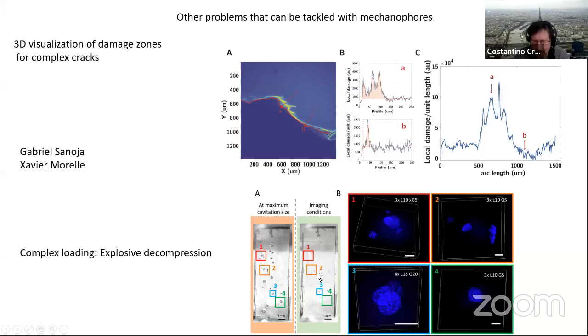And the second example is, I think for me, another fascinating case: cavitation, the explosive decompression. You saturate the rubber with gas, and then once it's saturated, you decompress rapidly. This is something that the oil and gas industry does. And then all these cavities close down, so you have no idea that these cavities ever existed. But now if you have a mechanophore, you can look at the sample with cavities closed and observe the shape. One of the things that we found is that these cracks actually have disk-like shapes. They do grow as cavities, but the damage zone is very much a disk, like a penny-shaped crack. And we can look at some of the details of how they grow.